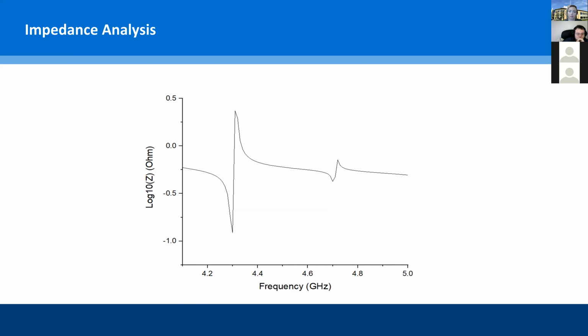One of the good news in this project is that we have got resonant frequencies beyond 4 gigahertz. You can see there is a fundamental mode contributed by the zinc oxide layer, which is the transducing layer. There is also another mode which we suspect to be contributed by the zinc oxide layer along with the silicon dioxide layer, but we are not yet sure about the second mode, because it requires a lot of experimental work. We could clearly see that the resonating frequency of the fundamental mode contributed by zinc oxide is around 4.1 gigahertz. That means we could detect really very small masses, equal to the mass of a single virus, which would be in several femtograms.